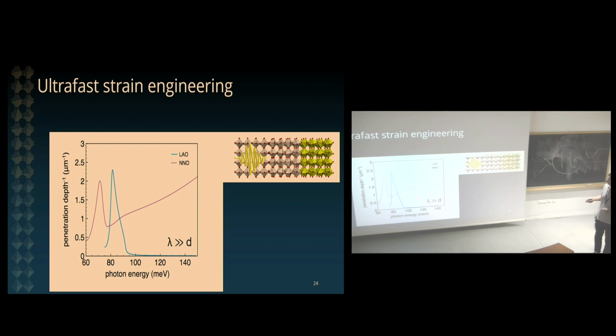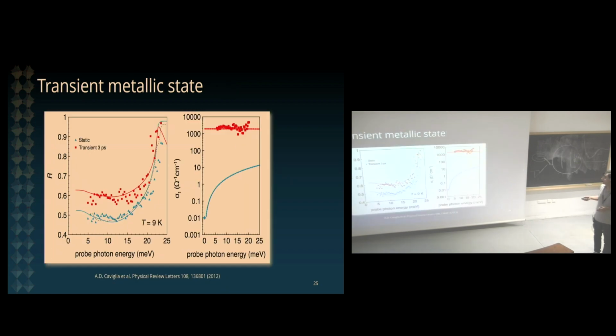Right, and so the idea of the experiment is to excite the phonon mode of the substrate. So here I'm showing you at the same time the phonon peak of neodymium nickelate and the phonon peak of lanthanum aluminate, plotted as a function of the penetration depth. And you see that these two are well separated. So we can tune our excitation light to be resonant with one or the other. So we can specifically address the lattice of the substrate.